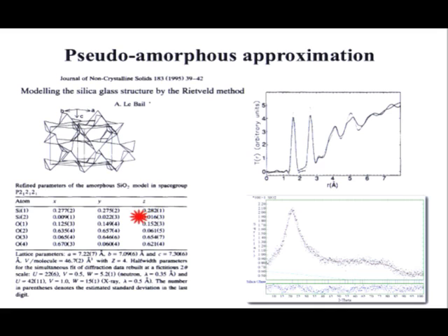So now, Anne mentioned before, okay, how to use the Rietveld with the Lebail approximation or the X-ray amorphous, right? So Lebail came out with this fact that you can use a crystal structure, and you distort it from the amorphous point of view, simply enlarging the peak shape. So it means you choose a very small crystallite size, microstrain, like it is a nanomaterial, okay? So it's pretty easy to use in any Rietveld, straightforward. The only thing, you need the crystal structure, so the local structure of your amorphous. So you need to model it.